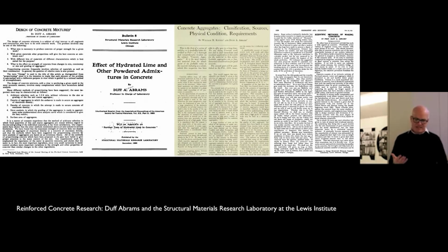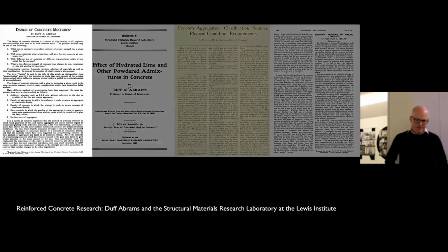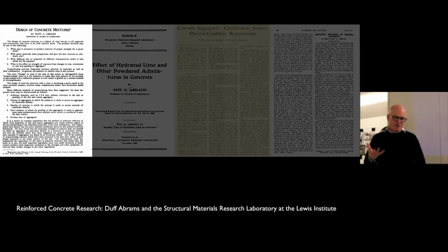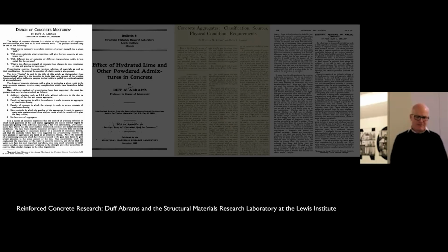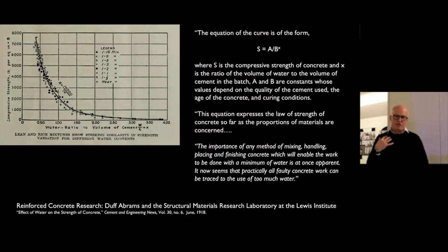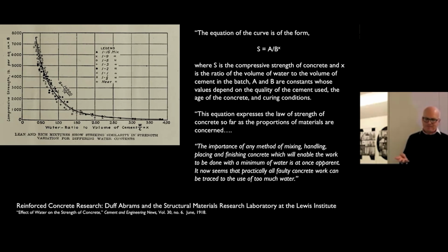They churn out a couple dozen papers, one of which in particular, Design of Concrete Mixtures. The Portland Cement Association a few years ago did a poll, like what are the top, like 20 innovations in concrete. And this paper was listed in the top like 4 or 5. And the reason for that is that Abrams discovers, as he is preparing all of these mixes, that what's been left out of the equation, right? If you think 1 to 2 to 4, cement, sand, aggregate, there's a fourth ingredient, and that ingredient is water. And Abrams says to this point, the codes, the specifications have all said, just put enough water in to make the mix pliable, make it into a liquid.